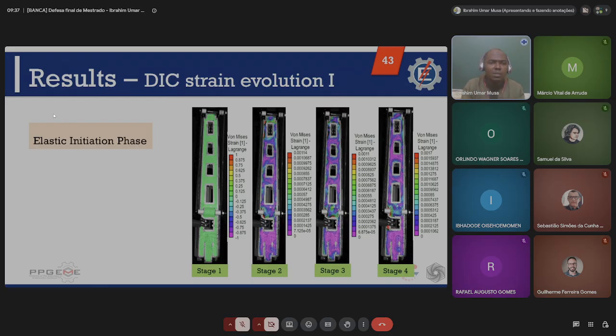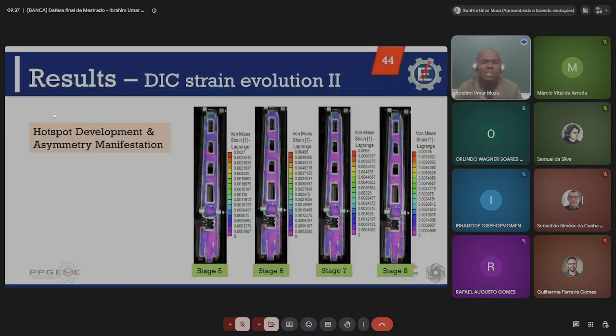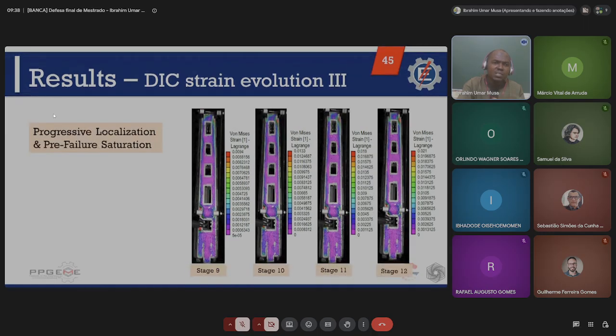Now we have the strain evolutions also from beginning to the end, and these were subgrouped into three. The first evolution presents the elastic initiation phase from stage 1 to stage 4, and the second evolution presents the hotspot development and the asymmetry manifestation as a result of the load fixtures. And we have the final stage, which is the progressive localization and pre-failure saturation.